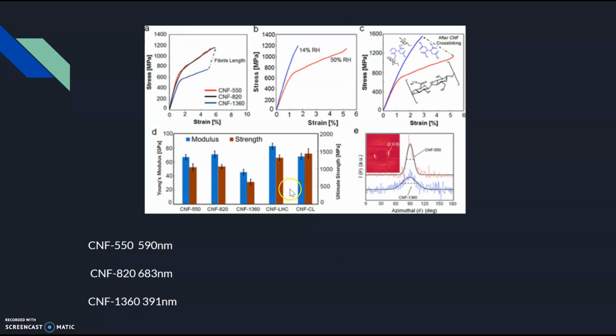This next image right here shows the comparisons between the cellulose nanofibril lengths. So the CNF 550 has a length of 590 nanometers, CNF 820 is 683, and CNF 1360 is 391 nanometers. What they found is that the shorter the nanofiber length, the worse it did. And the reason why the CNF 550 and the CNF 820 were able to perform so similarly was due to the average lengths being pretty similar. So that's what this shows here.